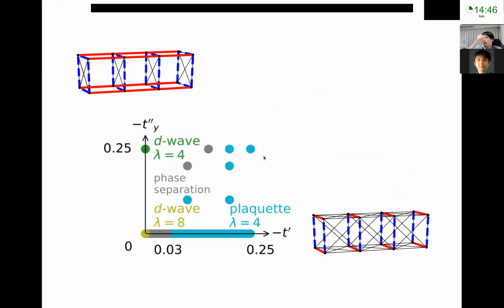Now we provide a rough phase diagram considering different strengths of T-double-prime on the plaquette and T-prime on the surface, and we find that with larger T-double-prime, the plaquette parent gets pushed back by the larger T-prime. So this shows that the T-double-prime tries to stabilize the surface parent - this cross hopping pushes the superconductivity away from the plaquette.